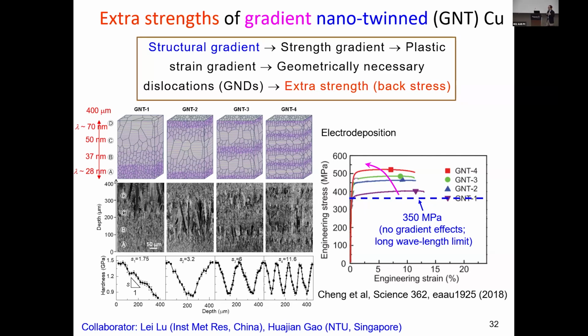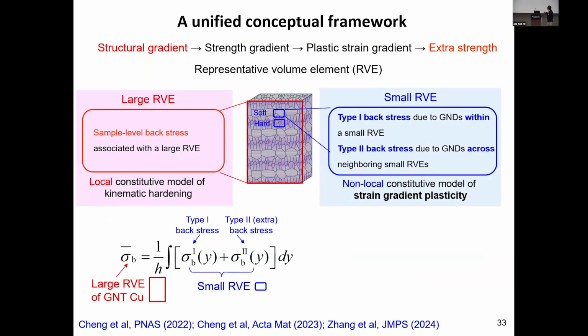Now we have this so-called plastic strain gradient. This plastic strain gradient needs to be accommodated by geometrically necessary dislocations, like charges of the same sign. They collectively produce this directional back stress effect. So our quantitative study shows that most of the extra strengthening effect due to the increasing structural gradient arises from this back stress strengthening effect.